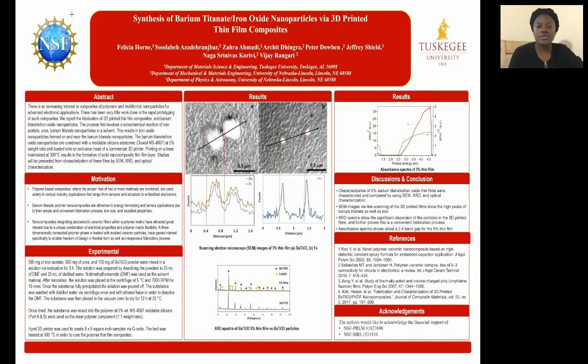So from that, I was able to infuse the particles in this two-part moldable silicone, part A and part B. The ratio for that polymer was 1-to-1. And the weight percent for the nanoparticles was 5 weight percent that we put into the polymer, which again was mechanically mixed. So we were able to get this polymer via a syringe, and I got 5 by 5 square inch samples to put on a hot plate via a Hyrel 3D printer in order to get these thin films. So from that, that's how we actually were able to fabricate this polymer, and then go on from there to get these characterizations of SEM, XRD, and of course optical.